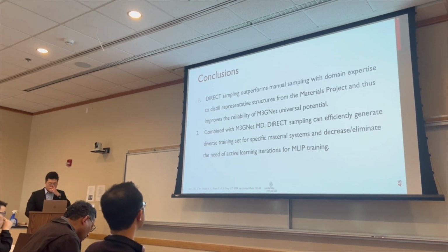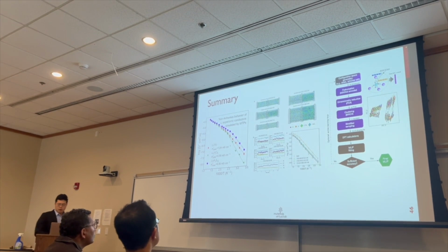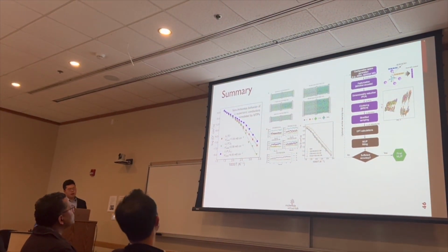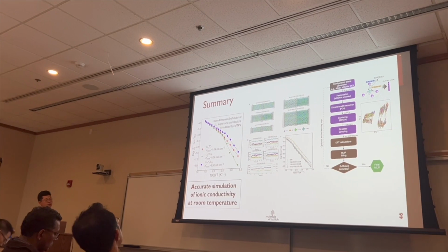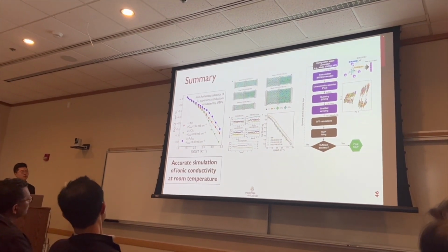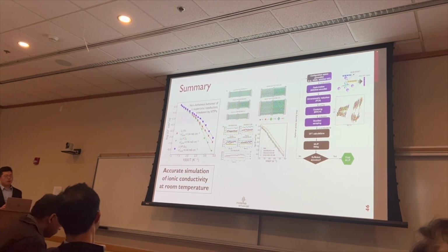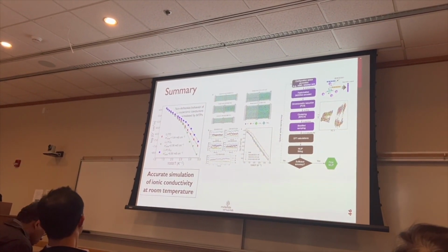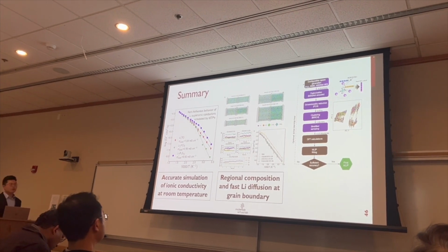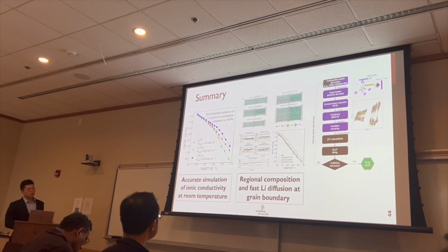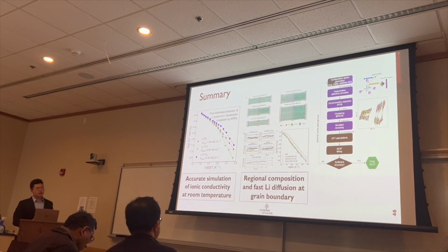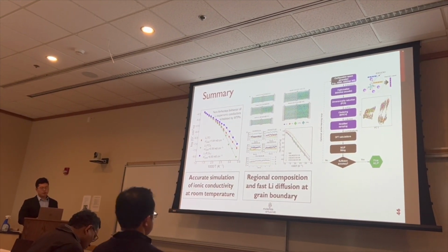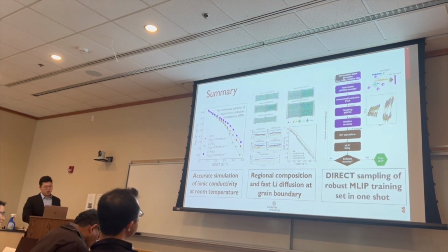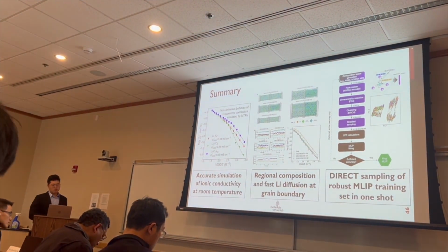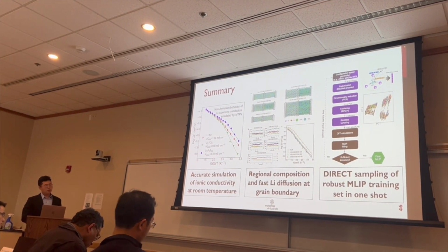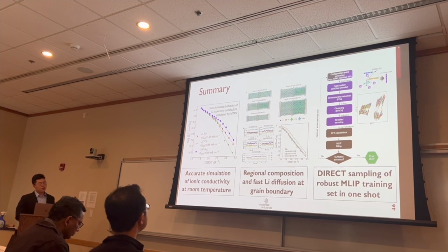Okay, so I will go to the summary slide to summarize what I've done in my PhD for the defense. Firstly, we investigate the method to use MLIP to do accurate simulation of ionic conductivities at room temperature. And in the second project, we use active learning to fit MLIPs to study the regional composition and fast lithium ion diffusion at grain boundaries of solid electrolytes. And in the third study, we come up with this direct sampling method to do robust MLIP training, to generate a robust MLIP training set in one shot.